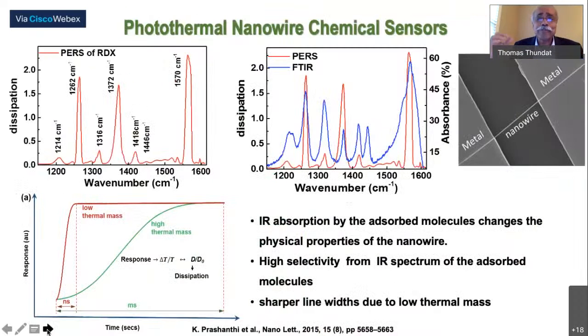We can also make the thermal mass even smaller. Then you lose the resonance frequency because it gets harder to measure the resonance frequency without complex equipment. So this is a nanowire, and you can do the same thing, expose it to different wavelengths. In this case, the RDX is adsorbed on the nanowire, the red is the nanowire data, and the blue one is the FTIR spectrum. You can see that the spectrum of the nanowires is much sharper compared to FTIR, because as we make the device thinner and smaller, with lower thermal mass, the response time is faster, and you can see the resolution in time get much better. That's what is shown here.